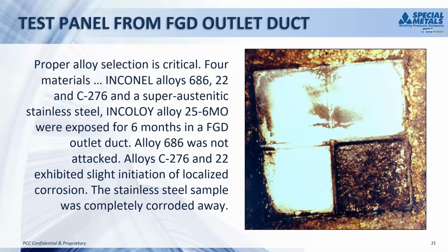In this case, the 686 was not corroded, and there was initiation of localized attack in the 22 and the C276. So I guess the message that we could conclude from this is that a higher alloy provides much more corrosion resistance than a lower alloy. In this case, a thin section of 686 would have provided long-term service, whereas a heavy section, these samples were 6 millimeters thick. But if you had used 6 millimeters or 8 millimeters or 10 millimeters or whatever of the stainless steel, the life would have been still very short.